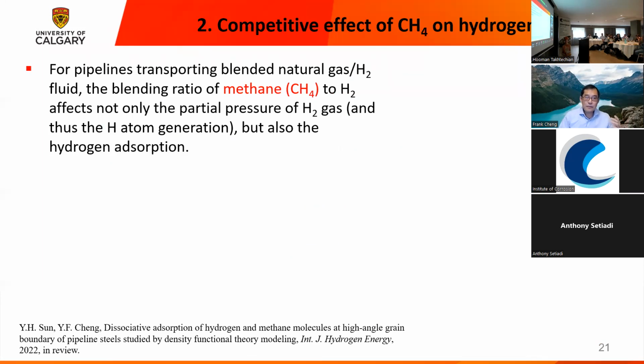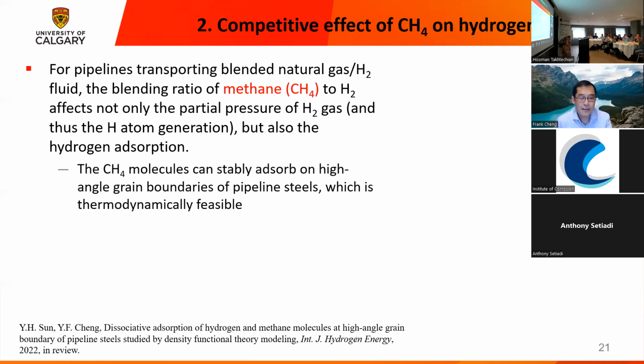The second, when we use the existing natural gas pipeline to transport hydrogen, the very quick question is how the methane, CH4, the main component of natural gas, will interact with the hydrogen, H2. Consequently, it will influence the adsorption and the dissociation reaction. So that is related to the influence of the two major gas components when we use a pipeline to transport the blended form. Okay, and in order to have this answer, the same thing, we also build a certain model to